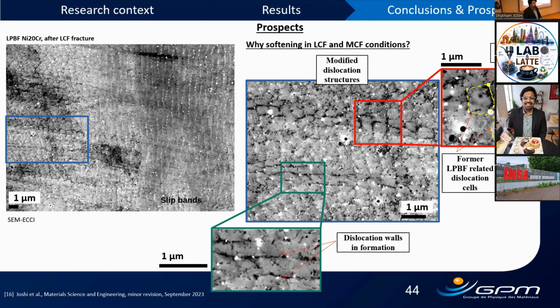So the chemical composition of the powder and of your cast sample is exactly the same? No, I think we have some carbon in the cast nickel-20 chromium, because the samples were bought directly from one of the companies. So we have some carbon. So it is not exactly the same, but more or less the ratio is right.